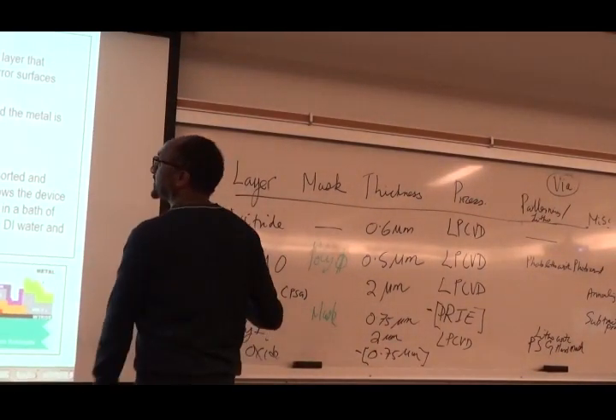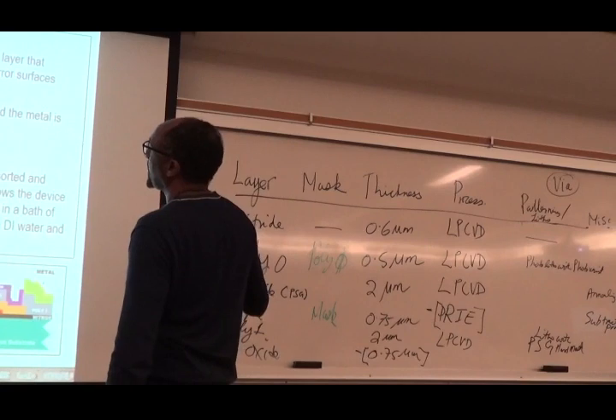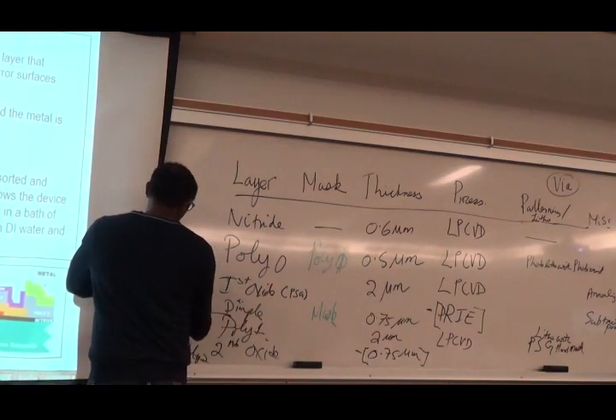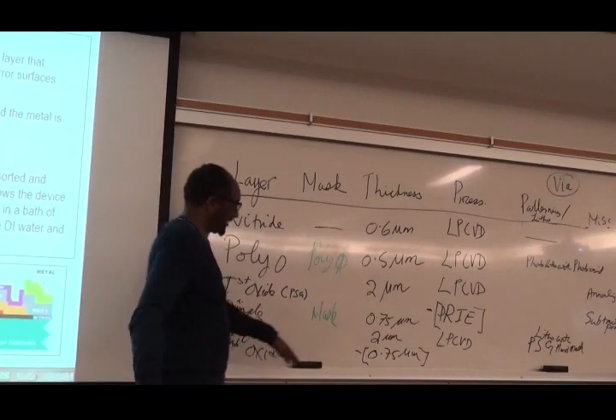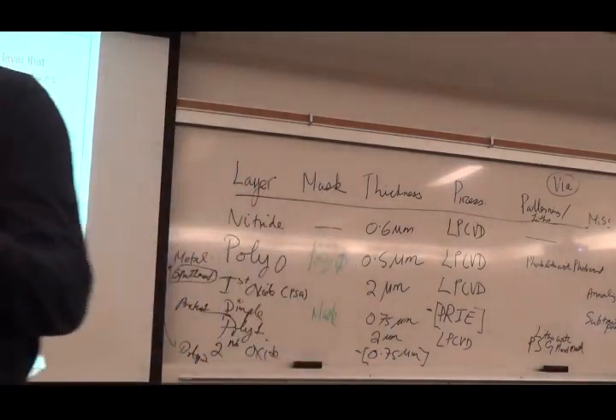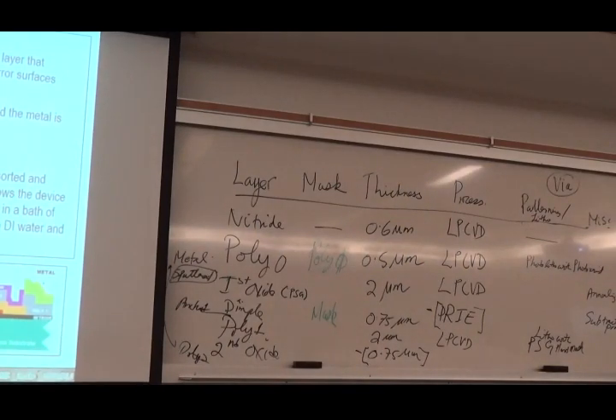Last step is metal, and metal is sputtered. Typically for metal, the layer is going to be about 50 nanometers. Somebody asked me about adhesion, about the metal layer. The typical metal that we use is gold. Gold does not attach to things very easily, so what you do is you have an adhesion layer, which is chrome.